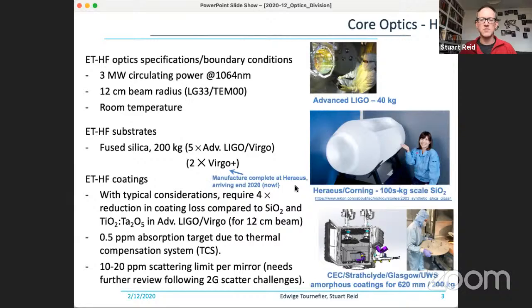And there are other companies, just following on the discussion about the availability of large substrates. For fused silica, we have 3 suppliers who are all trying to develop very large ultra pure silica ingots. So we also have Corning, Heraeus, which is a current supplier for many of our current detectors. And this is a picture from Nikon, who grew the largest silica ingot that they've grown. So for substrates, it certainly looks like the technology is there to fabricate very large silica substrates.